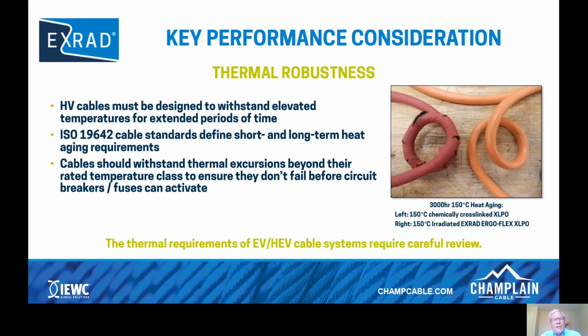High voltage cables must be designed to withstand elevated temperatures for extended periods of time. ISO 19642 cable standards define short and long-term aging requirements. The long-term aging requirement is 3,000 hours at the rated temperature, and the short term is 240 hours at a temperature that's 25 degrees C higher than the rated temperature. You can see the pictures on the right.